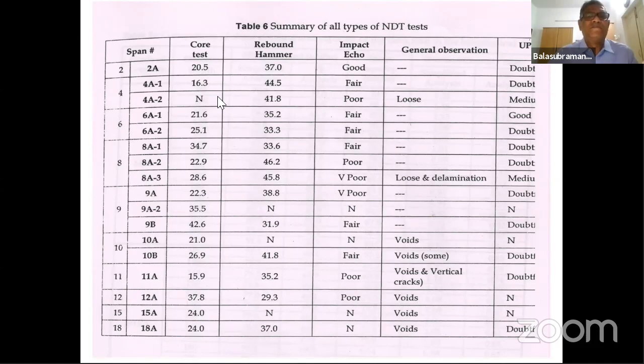If you look at the core test and the compressive strength predicted by a rebound hammer, you will always find that the rebound hammer predicts 2 times more or 1.5 times more. But there are instances where it predicts very close also. So, you need to take it with a pinch of salt. You need to be very, very careful when you want to use a rebound hammer in predicting the compressive